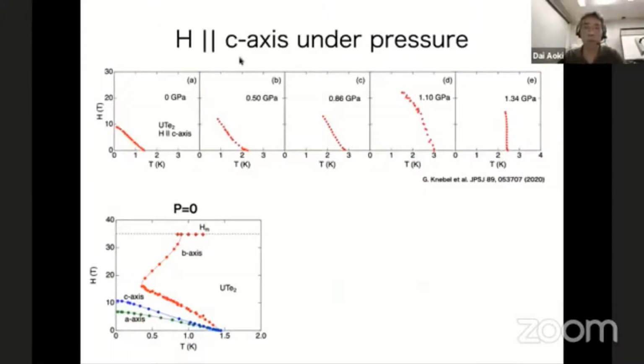Okay, so now I go to the C-axis. This is again the hard axis. For the C-axis at the beginning, the HC2 is about 9 Tesla or 7 Tesla. Applying pressure, you can see the slope of HC2 getting bigger and bigger. And at 1.34 GPa, it is almost vertical. This also indicates that fluctuation is very strong at the critical pressure.